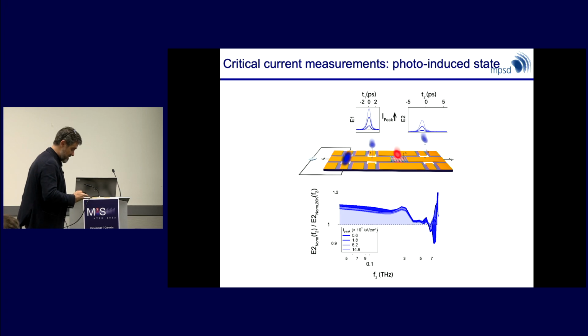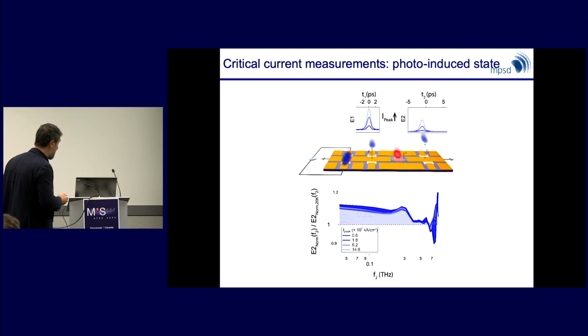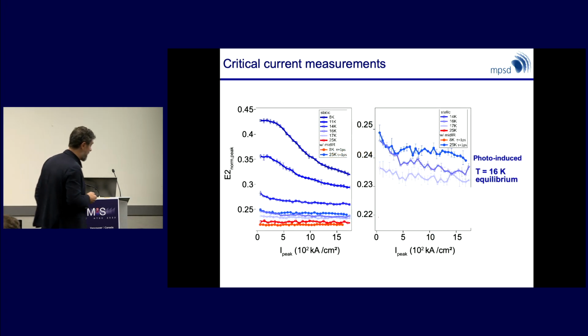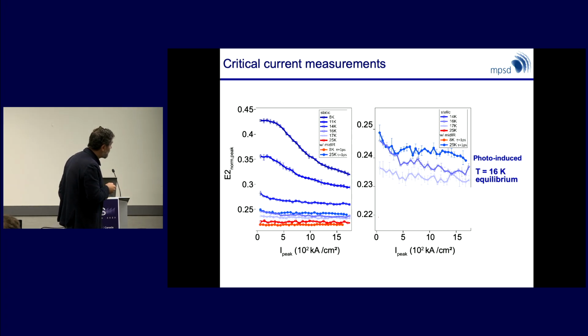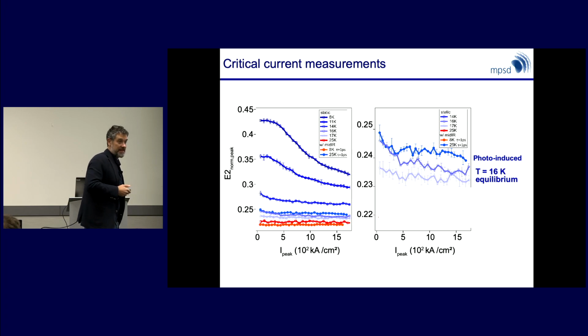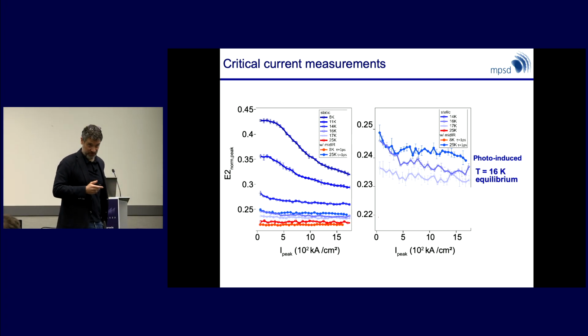And maybe these are preliminary data, but what is very suggestive is that if you take the critical current response at 16 Kelvin in equilibrium, and you show the critical current response of the photo-induced state, they're in the same ballpark. You see a reduction that is comparable. So this is where we are.